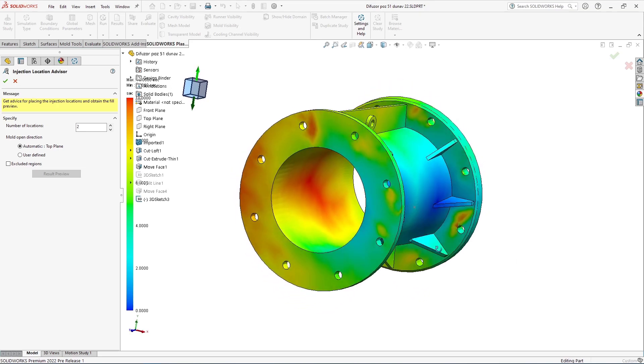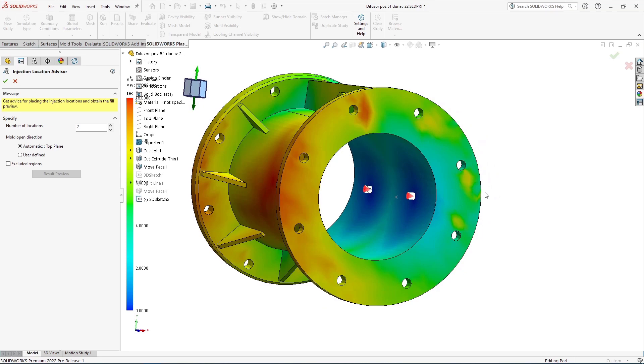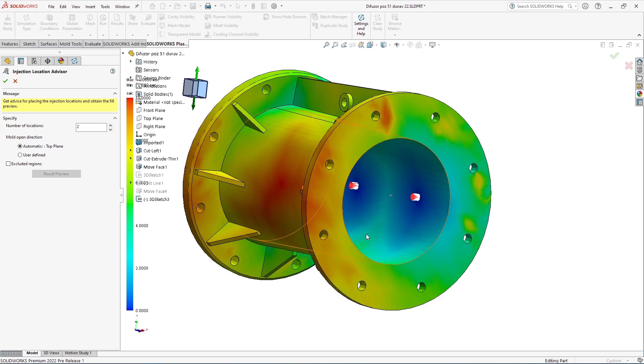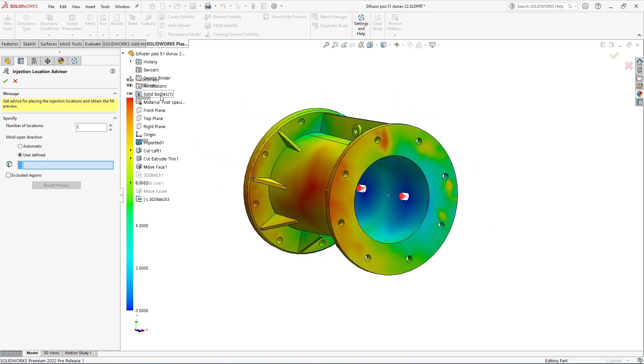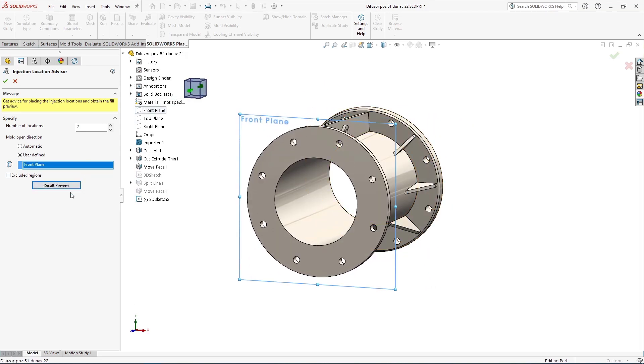You can see that Plastics is recommending that I place two gates on the inside of my mold cavity on the same half of the part, and that's going to possibly create a weld line right through the middle of the part that I don't want. So if I think I want to define my mold open direction in a different way — maybe I'm coming up with a new idea for the parting line — I can select a different plane for that and see how SOLIDWORKS Plastics updates its recommendation.